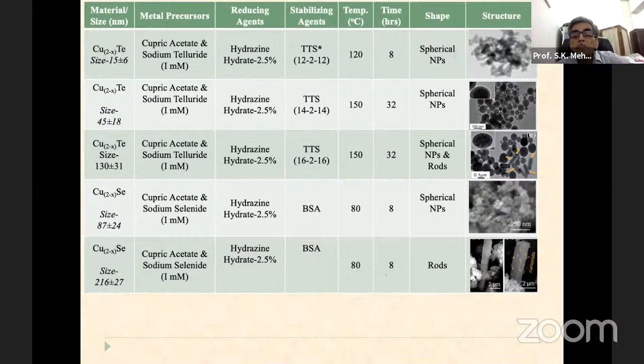Now you can see the shape can change if we change the parameters. You have the same here, but you can create copper telluride of size 130 by changing the system. You can also create a spherical nanoparticle. Here you get the rods. Here we have used the temperature 80 degree and time 8 hours, and we are using BSA and hydrazine as the same reducing agent, and you can get the rods. So you can play around to create different shapes of the nanostructures.